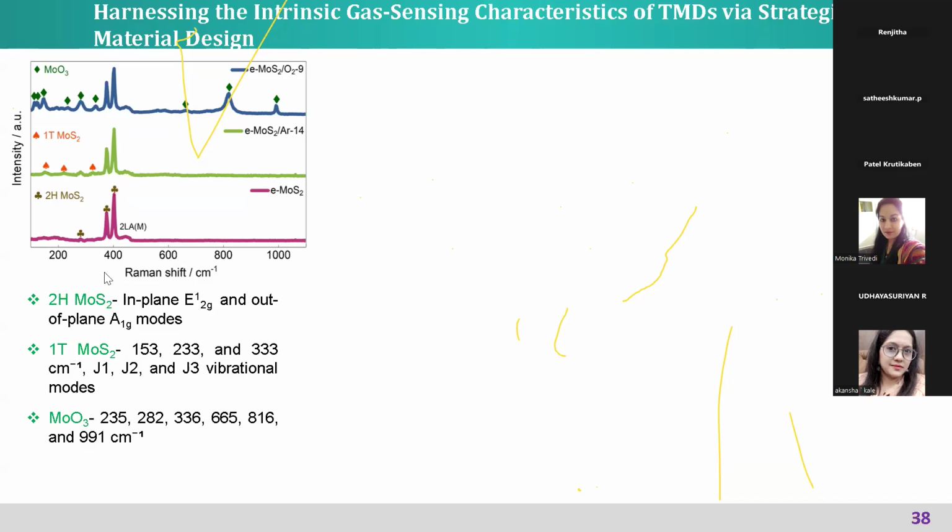By analyzing this Raman peak, one can find out what phase is present. This is the fingerprint method people usually use for 2D material characterization. Raman spectroscopy is one of the important techniques one has to use for analyzing 2D materials. When you do Raman spectrum, similar to X-ray diffraction, where you have characteristic peaks from different lattice planes, different crystallographic structures will give different Raman peaks. Those peaks correspond to different energy levels.